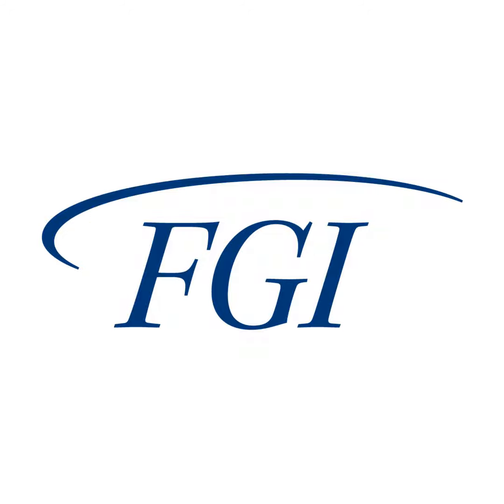Now, I was telling you that people in the ISO world prefer to use the flow capacity directly instead of the transmissivity. The reason is that Darcy's law does not apply to the flow in drainage geocomposites. You see in this little cartoon that the blue line shows what we know for soils. For soils, there is a hydraulic gradient and a flow which is directly related to the hydraulic gradient and the surface, and so on.